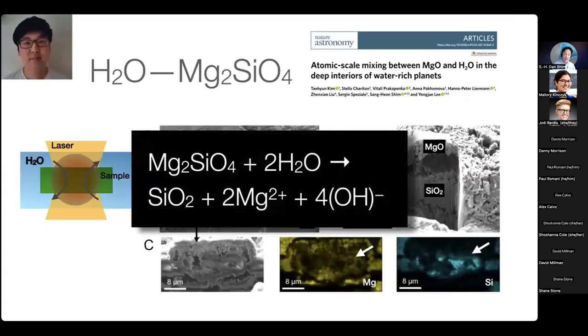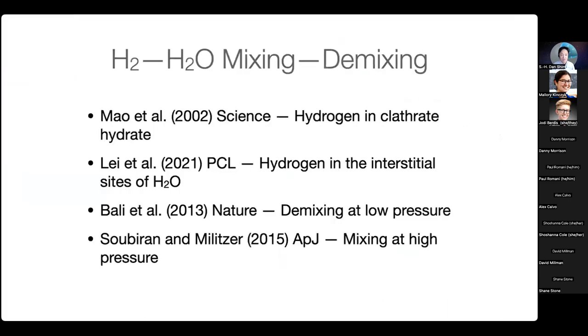We also studied the potential mixing between water and olivine, and we published the results a couple of years ago in Nature Astronomy. Basically, to summarize, when olivine is mixed with water and then laser heated for melting, we find that the magnesium dissolves into the water and mixes with it, while silica remains as a mostly solid phase, which means that if you have water and silica in the deep interior of ice giants, you'll have some degree of chemical mixing between rock and water.